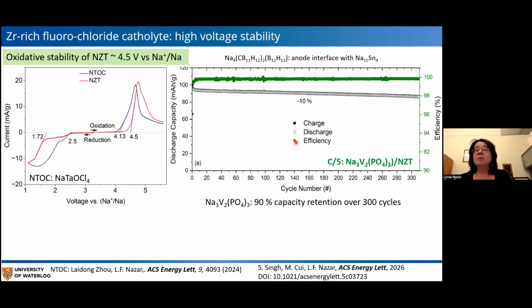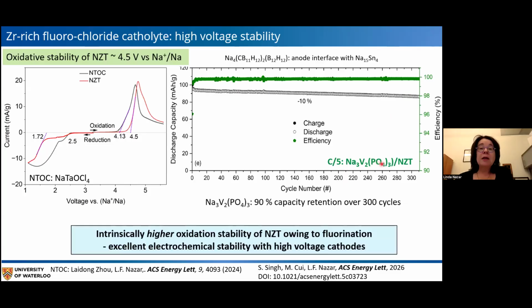And so then with this sodium vanadium phosphate, NVP as we call it, we see very stable cycling capacity, well over 300 cycles. And we can even take this up to higher voltages, to 4.4 volts, using a variation of this NVP, which is a higher potential. So the take-home message here is that we have intrinsically higher oxidation stability of this, our sodium, zirconium, tantalum chloride, owing to the fluorination, and good stability with high-voltage cathodes, such as this, or the oxyfluoride.